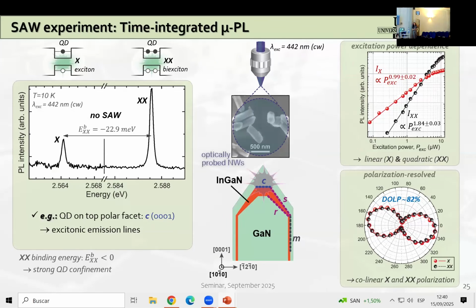Now, in order to show what happens when we apply the acoustic wave to these nanowire quantum dots, I will focus on the quantum dots in this polar topmost region of the nanowire, but we basically observe the same results for semi-polar and non-polar quantum dots. What I show here is just a low temperature micro-PL spectrum recorded on one of these nanowire quantum dots. And you see that it exhibits, again, very narrow lines, which correspond to the recombination of the excitonic complexes, including an exciton and biexciton, originating from one of these optically probed nanowire quantum dots.